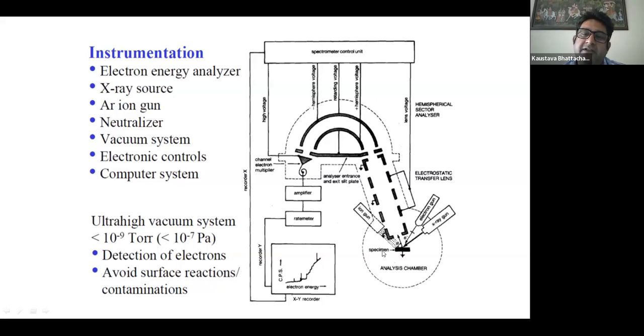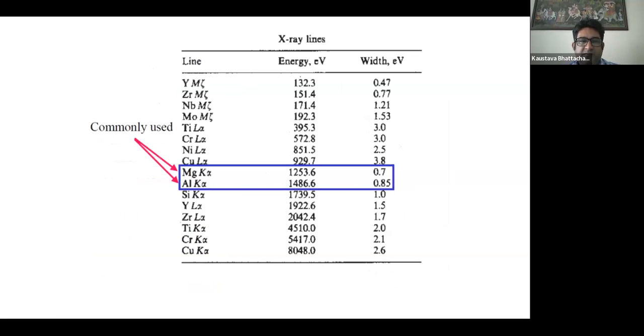If I know exactly from where the electron is coming and I know the theta, I can calculate the energy of that electron at every point. This energy is divided into smaller channels. Whichever channel it takes gives me the exact value of that particular energy, and I can calculate the kinetic energy of that moiety. The source, as I have told, that we usually take is aluminum K alpha and magnesium K alpha.